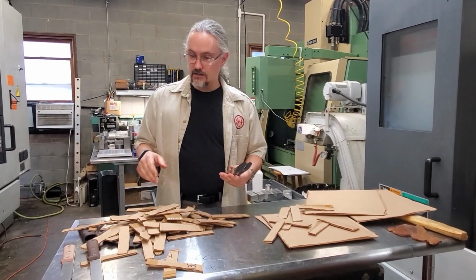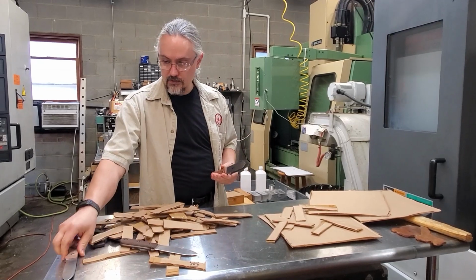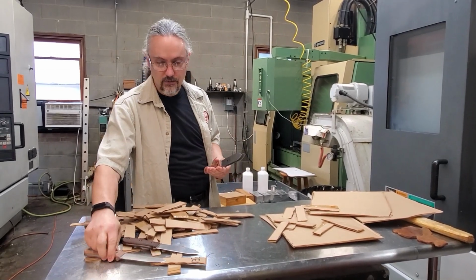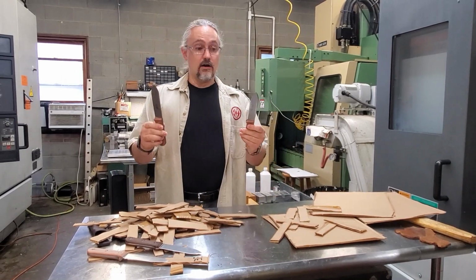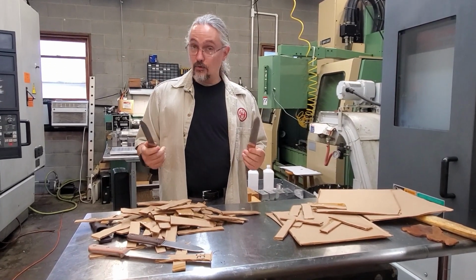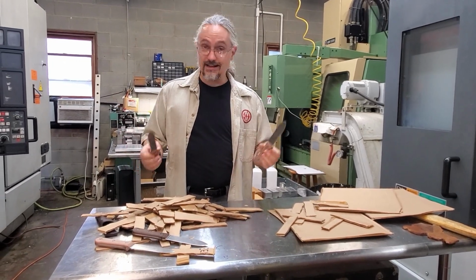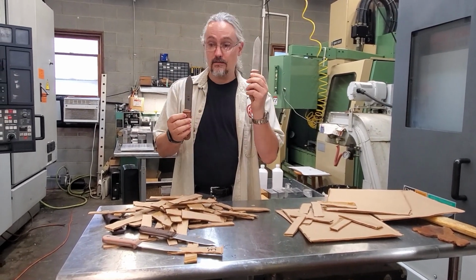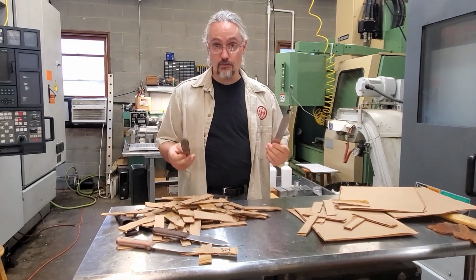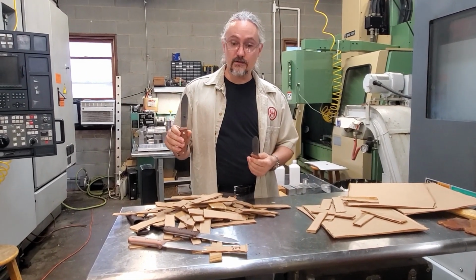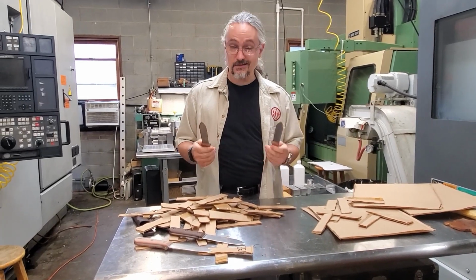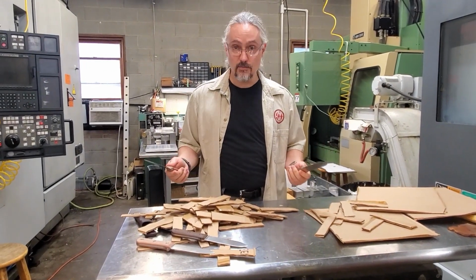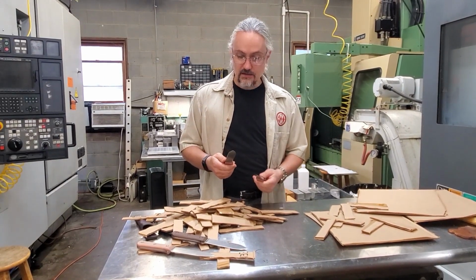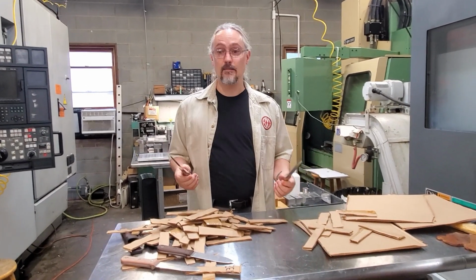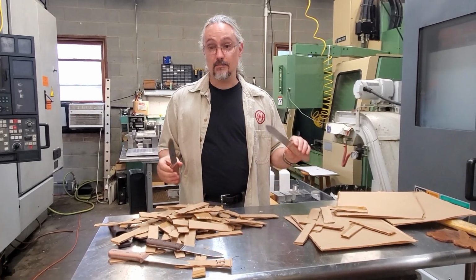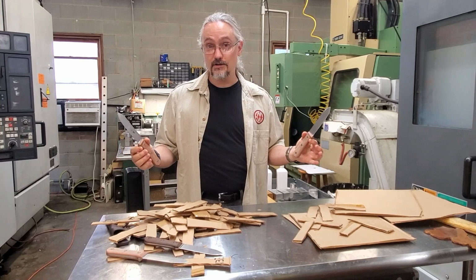But what you'll find is that a simple steel, like a carbon steel or a relatively simple steel, AEB-L, is going to start going dull faster. And your high carbide vanadium tool steels like 3V are going to hold an edge better in something soft and abrasive, but you're not going to see any real difference between, in my case, the Delta heat treat or your low temp tweak and the industry standard that uses a secondary hardening hump, because the abrasion resistance is largely baked in. There's not a whole lot that you can do about that. It's tied to the secondary carbides. You're not doing anything to the secondary carbides. You got, I don't know, probably 10% vanadium carbide by volume in one of these things. It's going to be abrasion resistant.